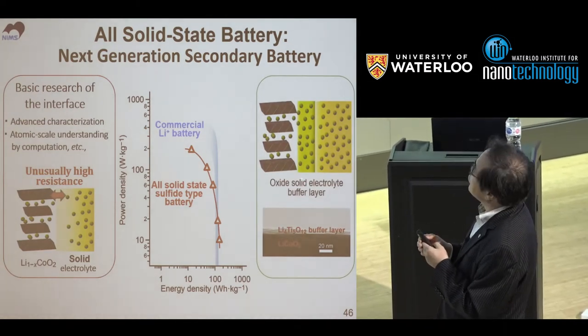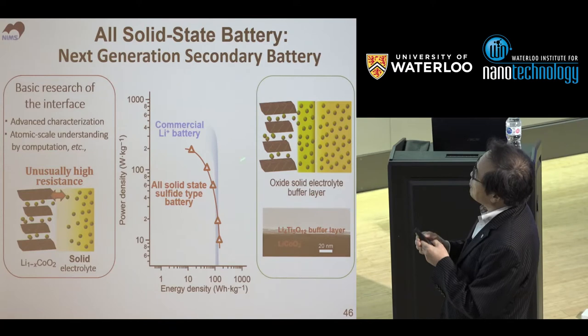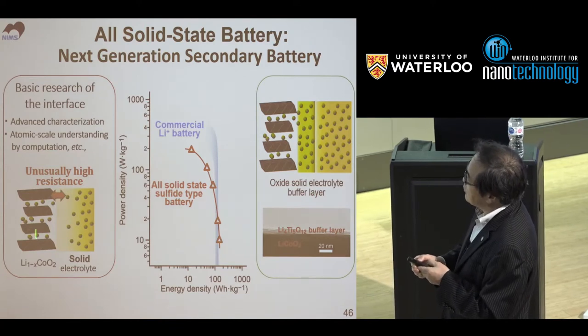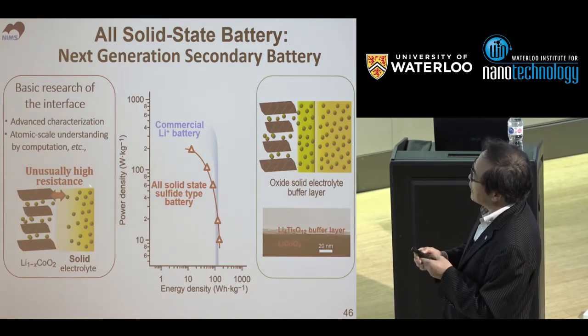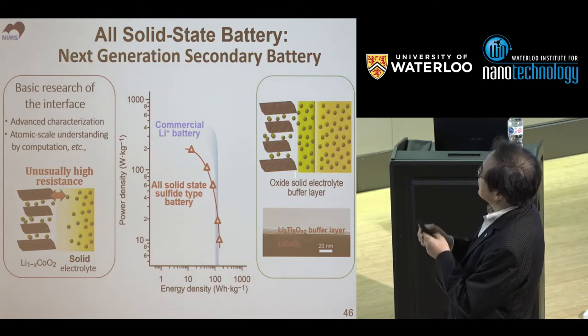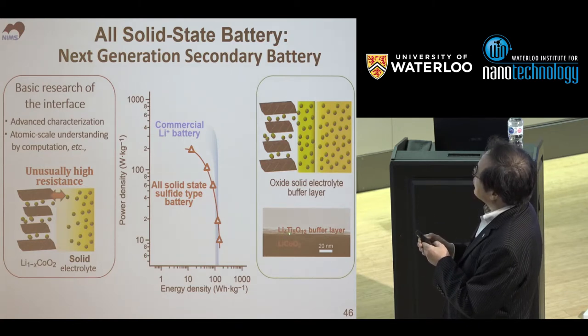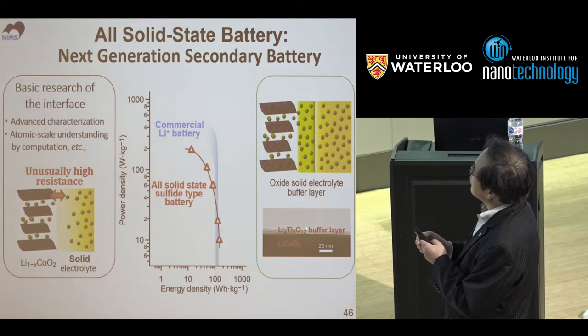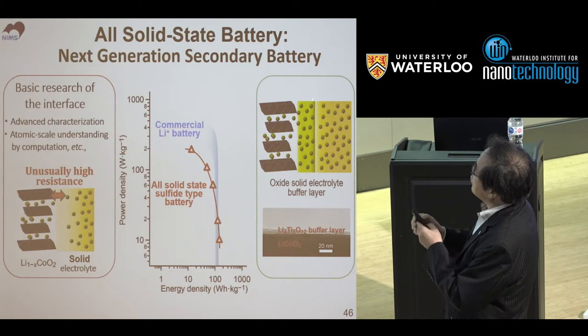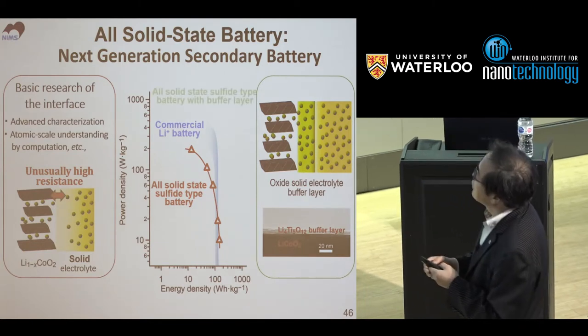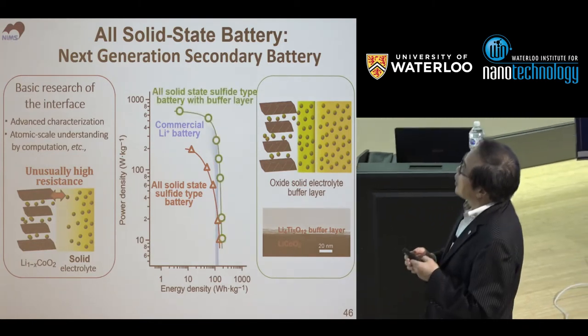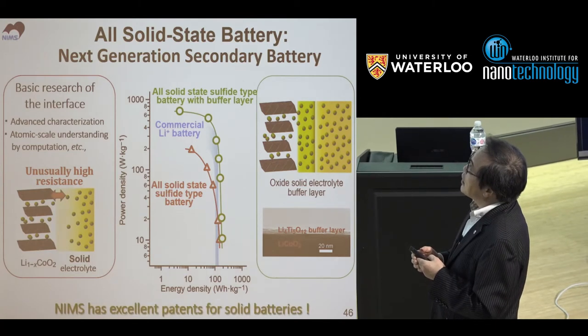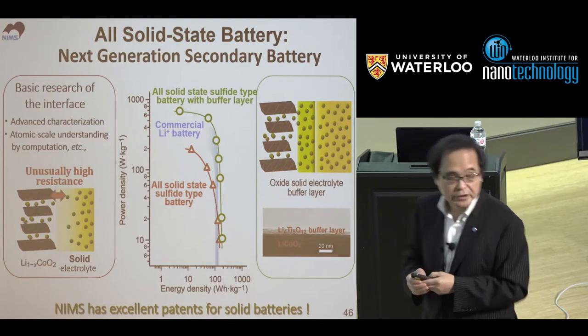To make a long story short, one of the researchers got the idea to introduce a buffer layer between this positive electrode and the solid electrolyte. Actually, a lithium titanium oxide buffer layer with a few nanometers thickness was introduced. Then the power density increased drastically and exceeded commercial lithium batteries.